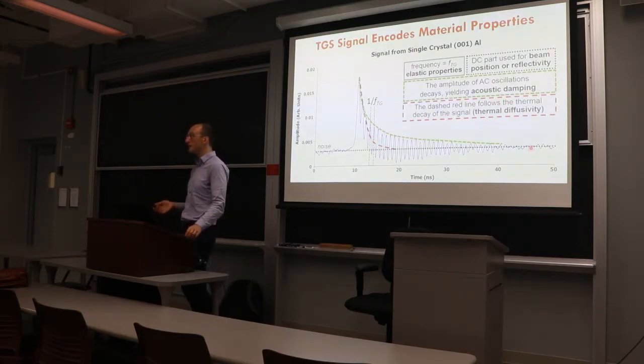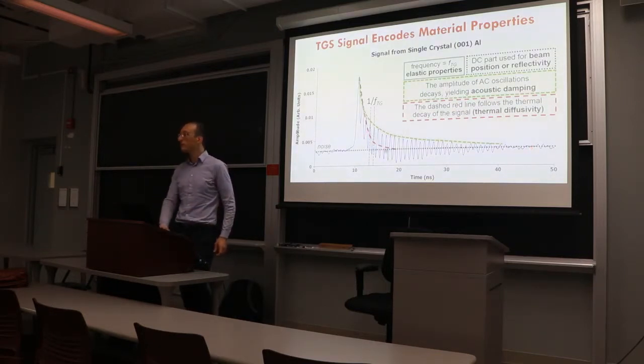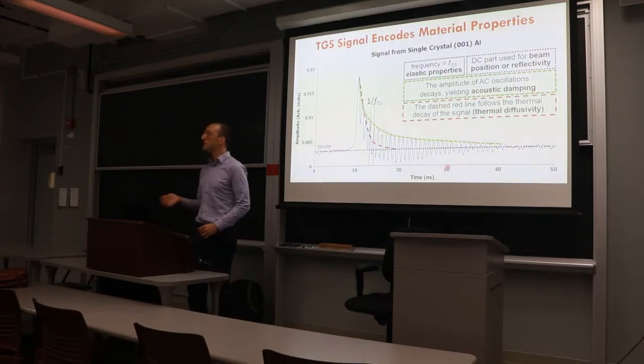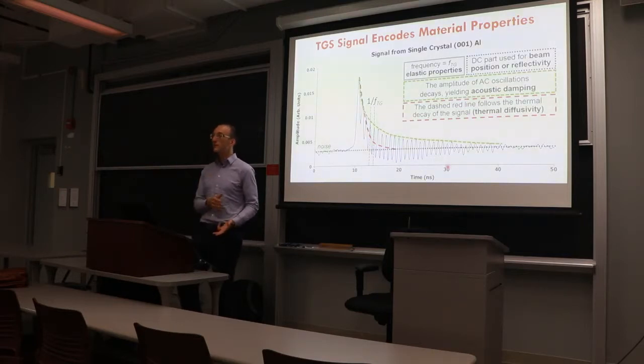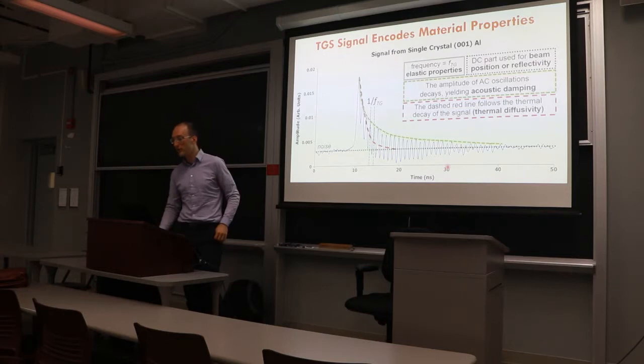Like the red line here: if you fit it to an analytical model, it gives you thermal diffusivity. The green line tells you the wave persistence, or the rate of energy dissipation of surface acoustic waves, which are supposed to be lossless, unless there's junk or precipitates in the way. And a Fourier transform of the blue signal gives you surface acoustic wave speeds. So you can watch the speed of sound, the Young's modulus, the Poisson's ratio, and elastic anisotropy change with radiation.